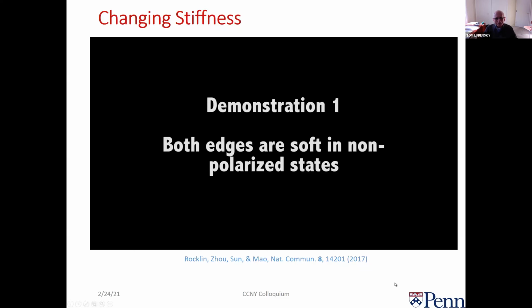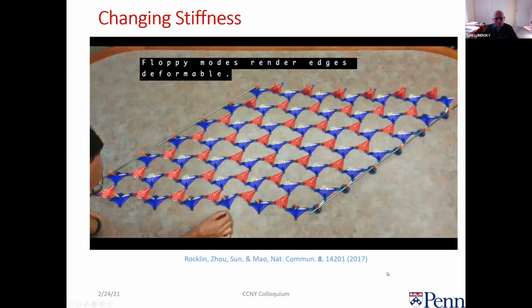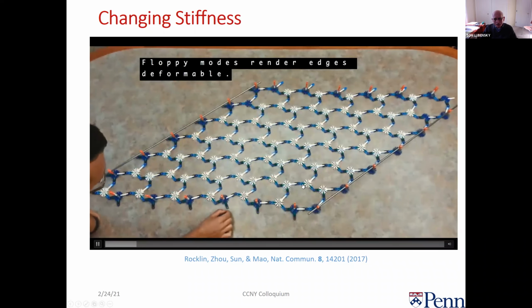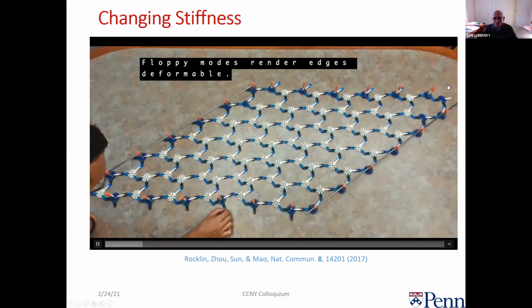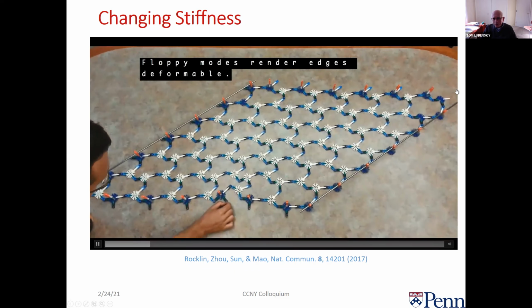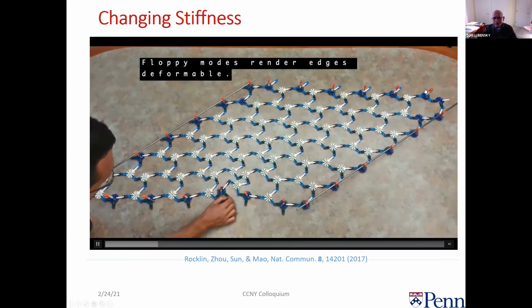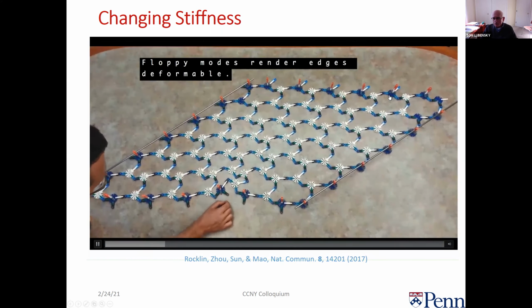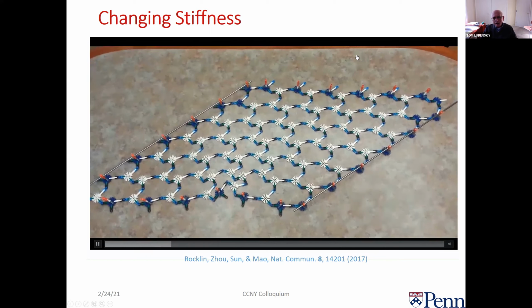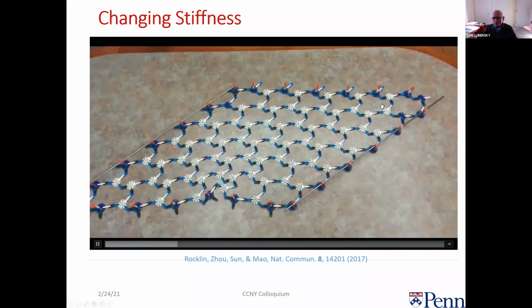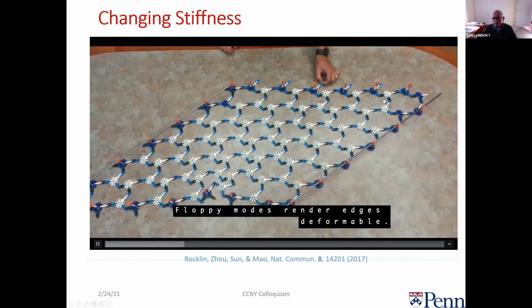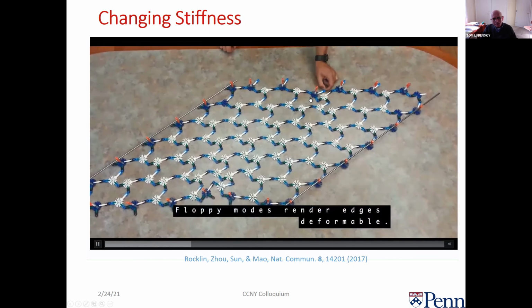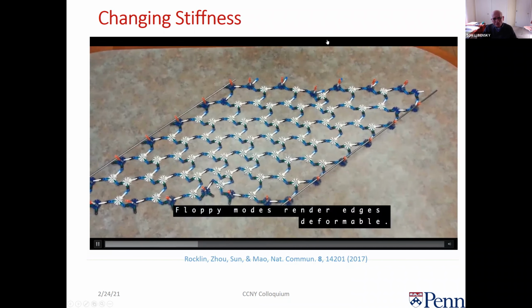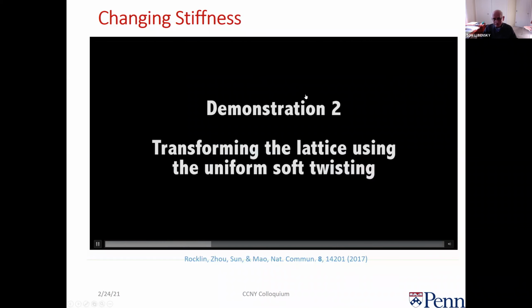Yeah, here we go. So we're going to make a material, this is the kagome lattice, but we've cut it. So now I no longer have periodic boundary conditions, and I have fewer constraints than there are degrees of freedom. In other words, the number of constraints is less than d times the number of sites. And you can see that there's a soft mode. You can push in the edges and it doesn't give any resistance.